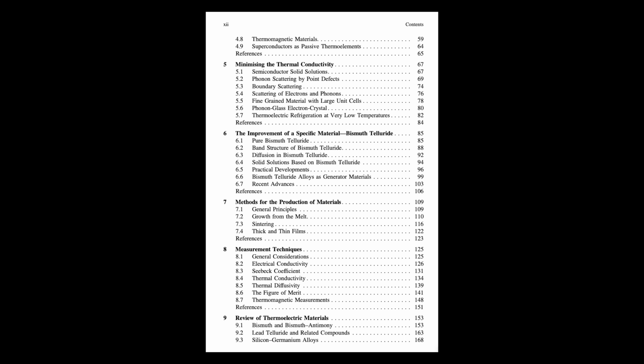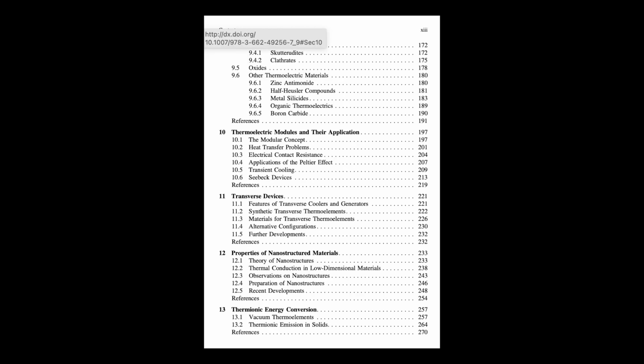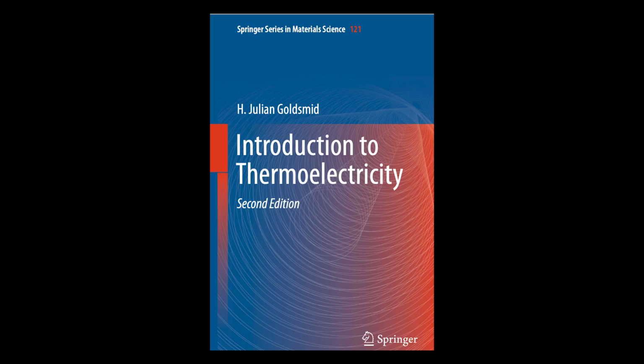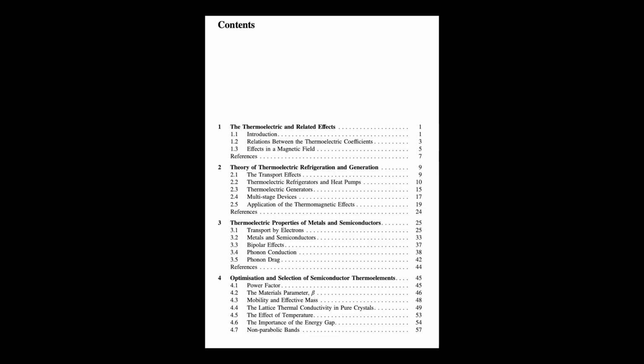Got it. Then we get into optimization, starting with the power factor, alpha squared sigma. How do we max that out? Right, the power factor, hugely important. It tells you how much electrical power you get out, generator, or how much cooling power you get, cooler. High power factor is essential. But here's the catch. Seebeck coefficient and electrical conductivity often work against each other. Like, if you add more dopants to a semiconductor, sigma usually goes up, good, but alpha might go down, bad. So optimizing is about finding that sweet spot, the right doping level or carrier concentration that maximizes the alpha squared sigma product.